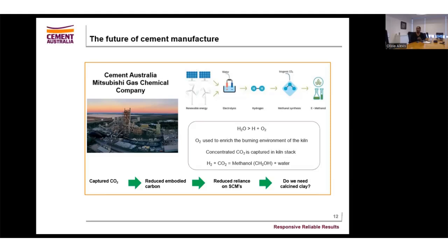Then the second phase of this process is using the oxygen in our kiln instead of the air that we currently use. The oxygen will be used to enrich the burning environment of our kiln. Then we'll be able to capture a high purity of CO2, and we'll provide that to Mitsubishi.